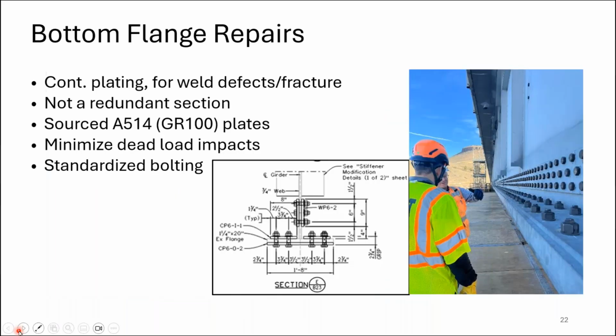These are the bottom flange repairs, and it consisted of these 5 plates, basically. So with bottom plate, 2 interior plates, and then these web crack arrest plates. This was not designed to be a redundant section or to have redundancy in the end, because it was really plates to replace any cracked section should a crack occur in the future. We sourced the grade 100 plates, as I said, but we were all bolted connections, so we didn't have any weldability issues in this modern steel. And then this allowed us to minimize the dead load impacts on the structure.